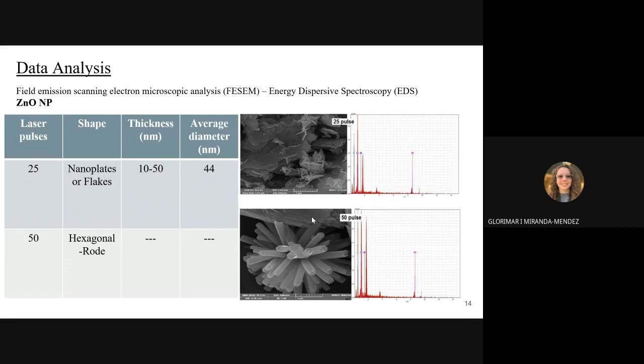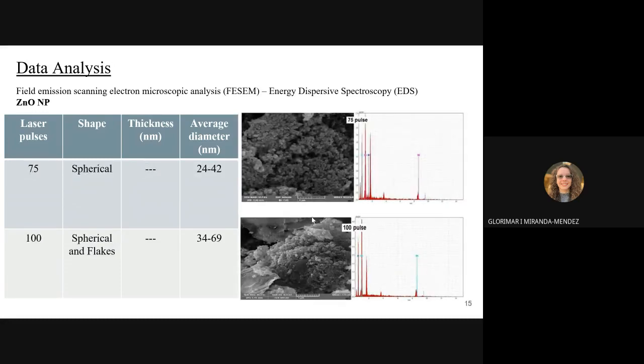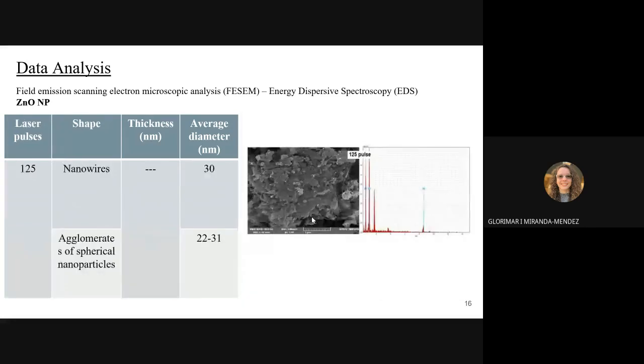For example, with the 25 laser pulses of the zinc oxide nanoparticles, they obtain nanoplates and flakes with an average diameter of 44, while with 50 pulses, they obtain hexagonal rod shapes. With 75, they obtain spherical shapes with average diameter of 24 to 42. And with 100 pulses, they obtain both spherical and flake shapes with average diameter of 34 and 69. With 125, they obtain nanowires with an average diameter of 30, but they also observed spheres that have a high agglomerate behavior with 22 and 31 as average diameters.